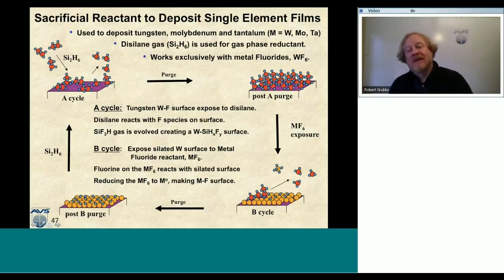Now I have this surface, and I come in with my tungsten hexafluoride or my molybdenum hexafluoride, and when I react that surface, the fluorine from the metal fluorides will react with all this silane on the surface to produce this trifluorosilane gas phase species.